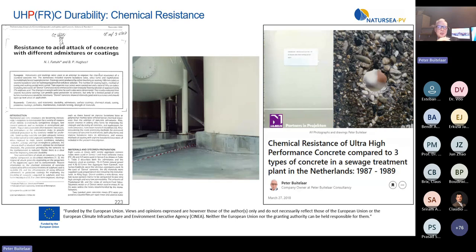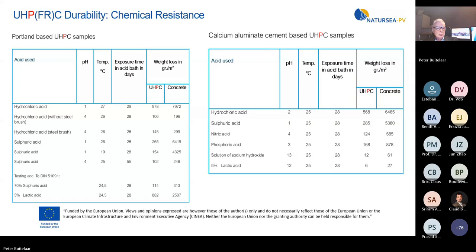Spillage of acids on industrial floors, industrial pavements and structures, but also in transport systems which have a wear lining is common. Early tests with different concentrations of acids and application in chemical plants showed a good chemical resistance compared to high quality concrete. UHPC tests with chemicals in various concentrations and at different temperatures show a good acid resistance compared to high quality concrete. Interesting is that UHPC made with aluminate cement often showed even a better resistance.